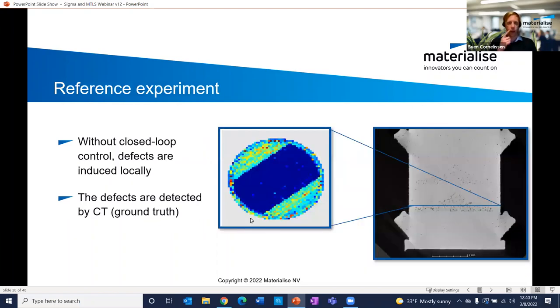So if you look at the experiment without closed loop control, which we call our reference experiment, where we run this job file but we don't yet enable our closed loop control, that's very important. Then in the center of this graph, you can see the Sigma Labs data, where you can clearly see that in the center, the energy density is much lower compared to the borders of this scanned layer. And of course, every one of these Sigma Labs plots is one slice through your real sample. And the real sample in this slide is represented by this screenshot of the CT scan that we did. And in this CT scan, you can really nicely see that we've actually introduced these two conical or pyramidical error shapes.